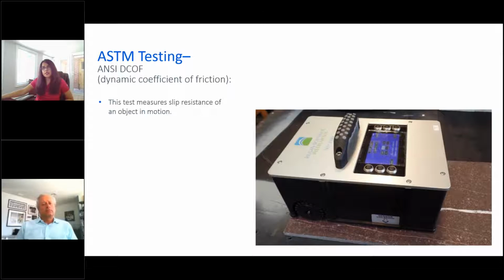ASTM testing still, but this one is an ANSI dynamic coefficient of friction test. This test measures the slip resistance of an object in motion. ANSI A326.3 states that hard flooring surfaces in level interior spaces that are expected to be walked on when wet shall have a dynamic coefficient of friction of 0.42 or greater for safe installation.